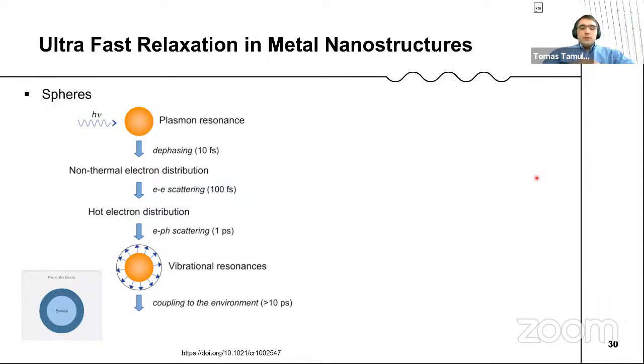And what is interesting with those nanoparticles, I just want to spend one minute here to explain what happens when you excite nanoparticles with femtosecond pulses. So they absorb the light, we have some dephasing of electrons, and then we have electron-electron scattering, and those are very fast processes and hard to catch if you have a pulse that is longer than 100 femtoseconds. But then those electrons start to release their energy by sharing it with the phonons. So we have electron-phonon scattering, and that heats up the nanoparticle.